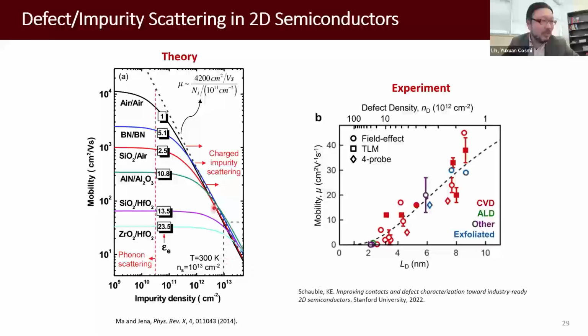So it's around room temperature. When the impurity density or defect density is from 10^11 to 10^13, you can see a great degradation of the mobility. This is the experimental result. The axis is a little weird, but it's essentially the same thing. Mobility versus defect density. The left-hand side is higher defect density, and we see a great degradation of the mobility.